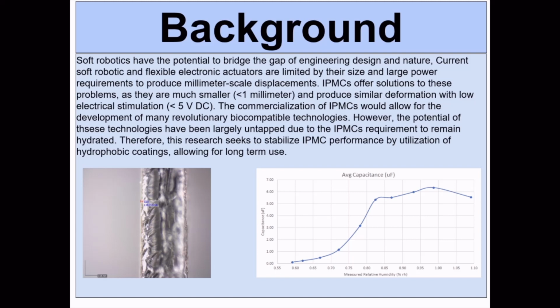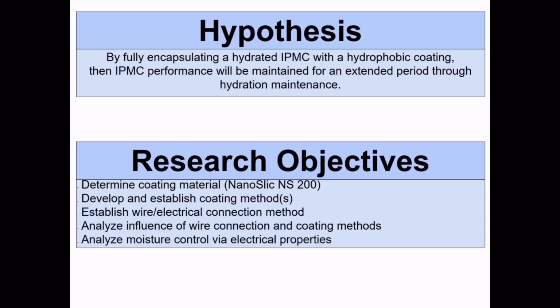The reason you don't see these everywhere in all these new biocompatible solutions is because the IPMC has to stay wet. And that is where my research has fallen this summer, and where I argue that if we fully encapsulate a hydrated IPMC with hydrophobic coating, then we can sustain its performance through a period of time.